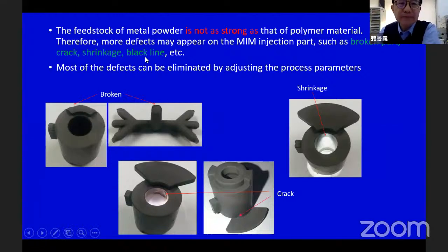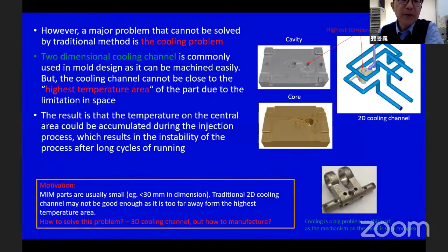But the problem is that because the feedstock of metal powder is not as strong as polymer material, there are more defects on this kind of green part compared with the polymer plastic part. For example, they are easy to be broken, there is some kind of sinkage on some of the internal holes, and a lot of cracks may happen on the part. Most of the defects can be removed during the process by adjusting the process parameters, but a major problem is the cooling problem. What is the cooling problem?